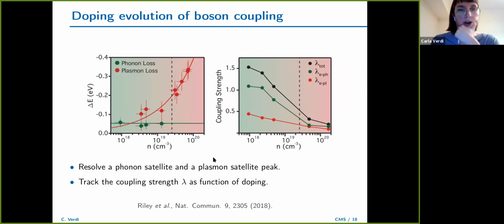From the experiment, you can actually extract the so-called phonon loss and plasmon loss. This is simply the energy separation between the satellite and the main peak. So you see that indeed, as I was telling you before, there is one peak that can be resolved that is due to the interaction with phonons, which is roughly at a constant energy. And then the interaction with plasmons instead gives you satellites with energies that increase with the doping, and it's actually compatible with this parabolic dispersion of the plasma energy.